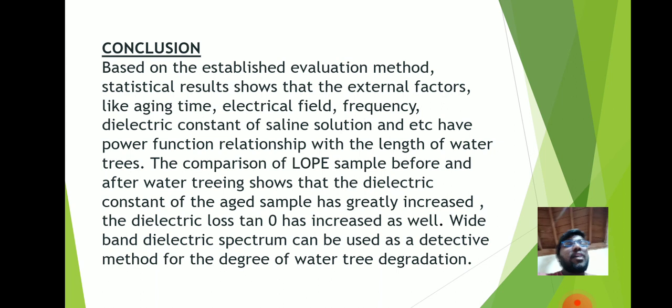We have done experiments and studied many graphs. Based on the established evaluation method, statistical results show that the external factors like aging time, frequency, electrical field, dielectric constant of saline solution, and so on have a power function relationship with the length of the water trees. The comparison of the LDPE sample